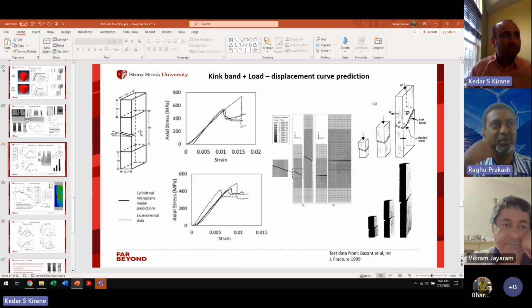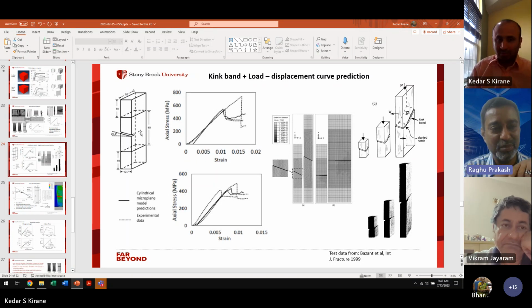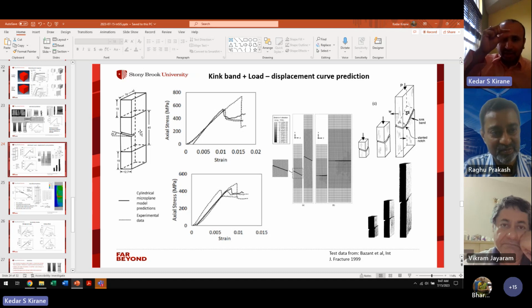But I remember earlier we used to have that, for the one at IITMRI or something like that, right? The compression fixture, which made strict regulations in terms of alignment and whatnot. Right. Well, another challenge is if you do a fracture test, if your initial crack is thin, what can happen is the faces will just touch each other, and then you can't continue with the test. So you have to have a wider notch so that the pre-crack faces don't touch each other during the test. So there are many of these considerations.